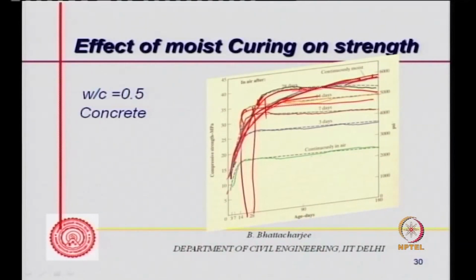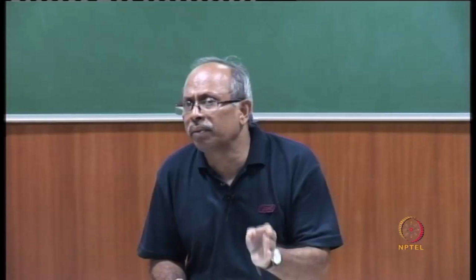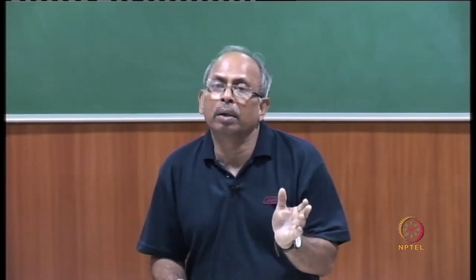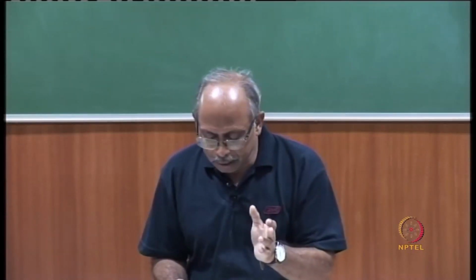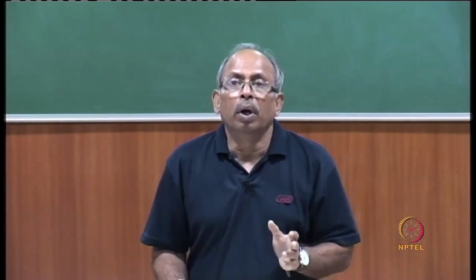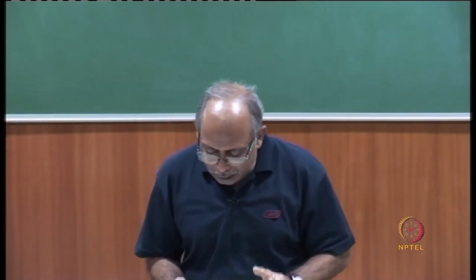Continuously in air, of course, strength development will be much less with time. Up to 3 days, there will be an increase, slightly more than 3 days. So what happens is, when you have stopped curing, hydration proceeds for a little while, and after that there is no further strength development. So therefore, strength development I need.